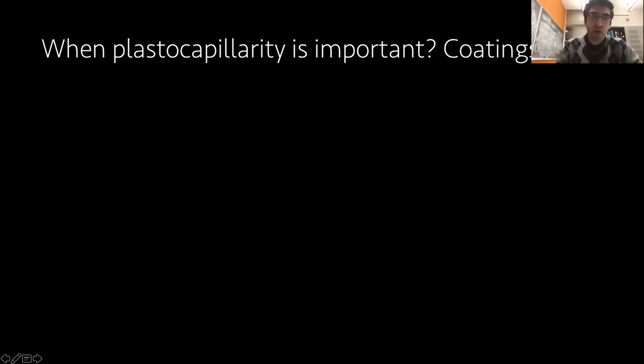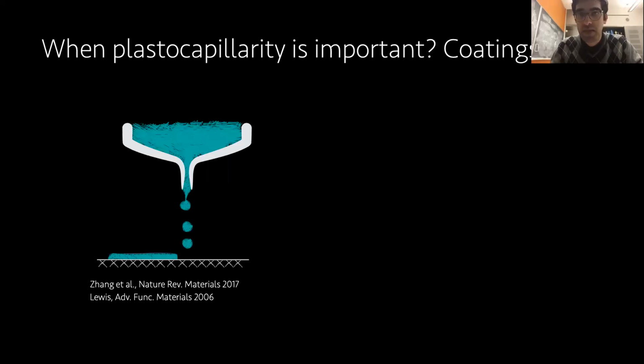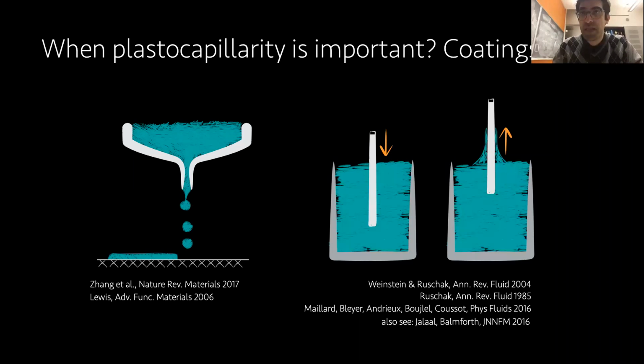Okay, more related to the talk today is the process of coating. There are many methods of coating fluids on a surface, and in many industrial applications, these fluids are viscoplastic, or at least show some non-Newtonian behavior. One way of doing so is inkjet printing, when you put single droplets on a surface one by one. A more common and well-known method is the dip coating method, when you have a piece of solid surface that you dip into your material and drag out, and then you have a thin film deposited on the surface. The thickness of this film is also determined by surface tension, and if your material is viscoplastic, by the yield stress. So this is a very nice problem to study plastocapillarity. Again, the group of Coussot looked into this problem, but in the regime they studied, surface tension, if I remember correctly, was not very important.